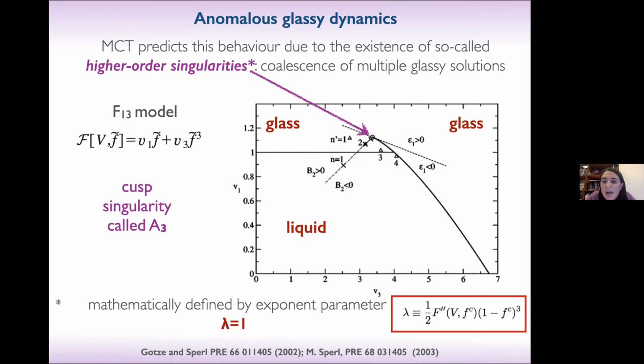And so what happens is that at some point this glass here and this glass here will become identical, will merge, and you will encounter a higher order singularity that by the shape of this phase diagram was called A3. It was called a cusp singularity, and in mathematical terms of catastrophe theory it is called A3. And you can mathematically define and calculate this higher order singularity because it is related to the second derivative of the functional. And when lambda, the critical exponent parameter, which defines also the other exponents a and b I told you before, is equal to 1, you have the equivalence of the two glasses.